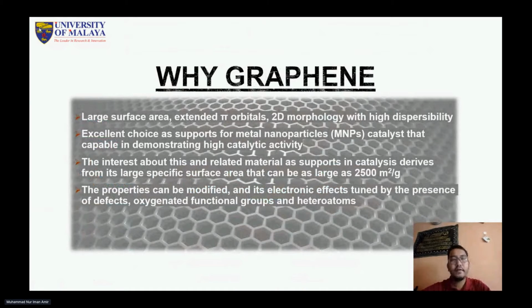The use of catalyst in that reaction is important, so I chose the combination of graphene and gold nanoparticles as catalyst for hydrosilylation reaction. Why did I choose graphene? Because it has a large surface area and a 2D morphology structure with high dispersibility. It is an excellent choice as support material for gold nanoparticles catalyst, of course, to demonstrate high catalytic activity, because graphene has a large specific surface area, so more gold nanoparticles can be attached due to the abundant oxygenated functional groups and heteroatoms present on the surface of graphene oxide.